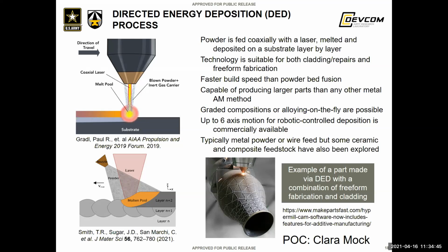So it's a lot more frustrating, I would say, than powder bed fusion, because you not only have the first order parameters, you can actually adjust the height layer to layer. So each layer is kind of individually made. If you wanted more local control of your laser processing parameters, this gives you a lot more wide open uses, because you control everything on an individual layer, as well as the way the powder flows into the part itself.